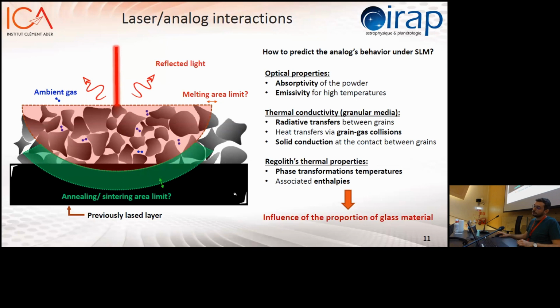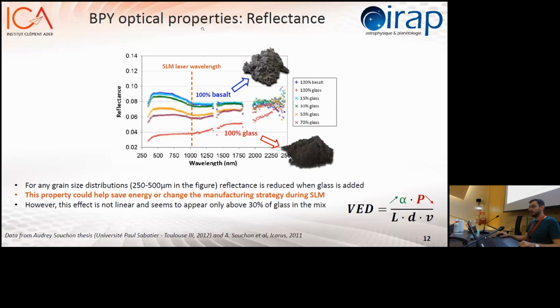And for all those properties, there is a huge impact of the proportion of glass you have at the beginning. For example, starting with optical properties, what you have here is the reflectance of our analog depending on its glass concentration. And so I'm not gonna discuss the behavior, the aspects of the curves, but if you stick to the SLM laser wavelength, you can see that just going from the 100% basaltic powder to completely glassy content, you are dropping from 8% of reflectance to 4% of reflectance. So in itself, it's already a good property for us because, of course, the more the powder absorbs the light, the less energy you have to spend to bring power to the laser.